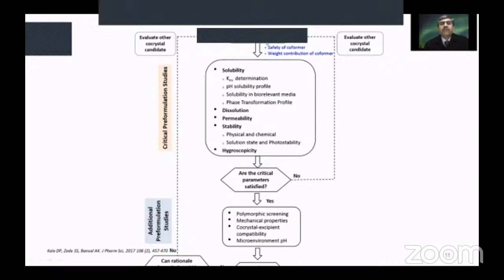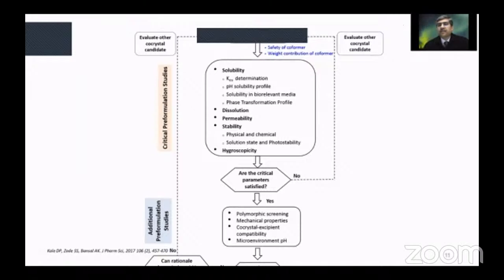If we have to pick the co-crystal candidate, the first thing that we need to see is the safety of the co-former. The co-former that has been used for creation of the co-crystal should not be unsafe to use in a pharmaceutical product. Also, the weight contribution of the co-former to the overall co-crystal should be within limits, because otherwise it will be difficult to convert the co-crystal into a final drug product, especially for high dose drugs.